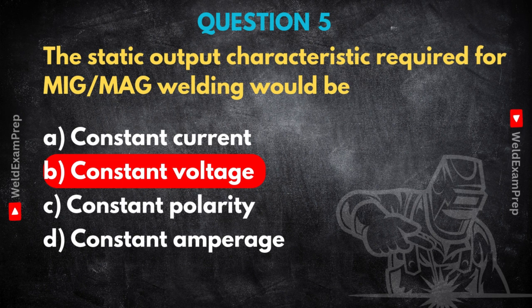Wow. Okay, that was quite a run-through. We covered lack of fusion in MIG stemming from multiple issues. Maintenance, settings, cleaning. The specific handling of E6010, no baking required because of that cellulosic coating. Right. The hydrogen is actually helpful there. Then, damaged MMA coatings leading directly to porosity because the shield fails. Yep. Atmospheric contamination. TIG welding non-deoxidized steel causing porosity from internal gas generation. From the oxygen and carbon reacting in the steel itself. And finally, the need for constant voltage power sources to enable that self-regulating arc in MIG-MAG.